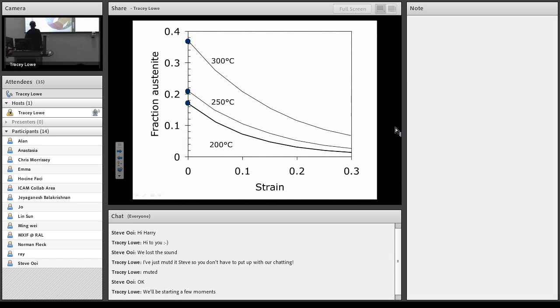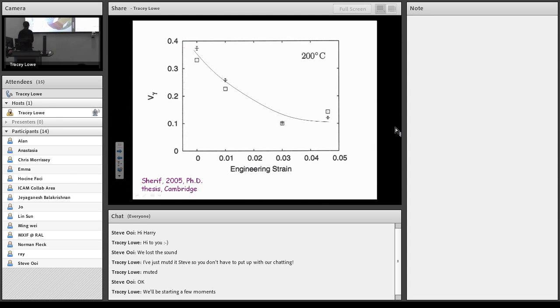And when we look at the point where these samples break, and we've done this also in situ in a neutron reactor so that we can follow these curves as they happen, basically, they all fracture when you reach a retained austenite fraction which is about 0.1. Okay? So what's magical about this 0.1? This is the in situ experiment inside the neutron diffraction kit, where we pull the sample, and again you can see that fracture actually happens when the austenite content decreases to about 0.1.